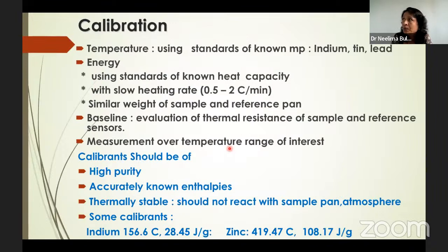As I told you, we are measuring heat capacity and temperature. So of course, calibration should be of the temperature and of the heat capacity of the sample. Along with our equipment, the manufacturers have provided us the standards. Standards are pure metals which have known melting points and known heat capacity also. So take a very small amount of that material and heat it with a very low heating rate.